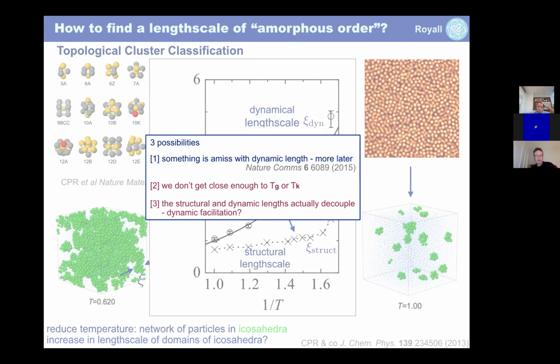So in fact, these are computer simulations, but they have produced a material with a viscosity of something like honey. And honey, and I mean the runny honey, okay, not the crystalline honey. So, this is not really a glass. This is just a supercooled liquid, but not a glass proper. So we would like to get much closer to the glass transition temperature.